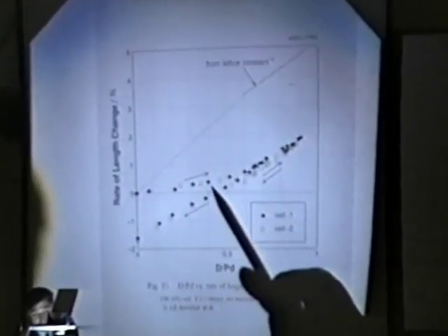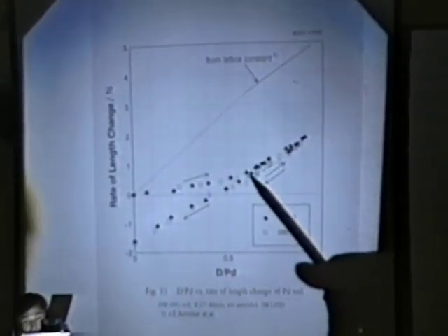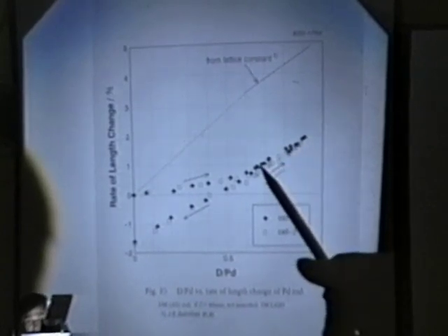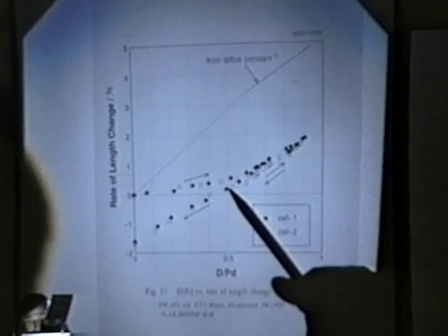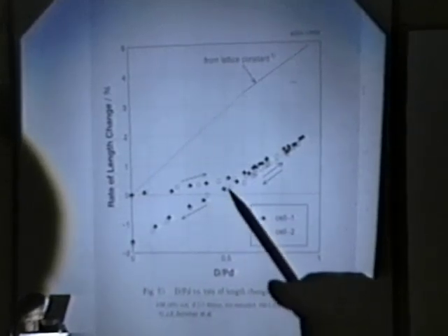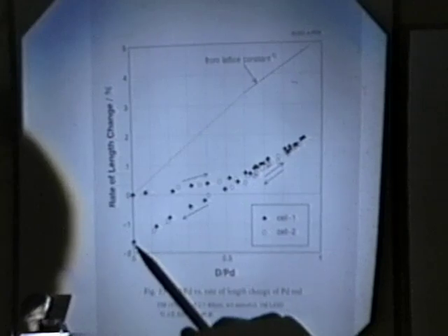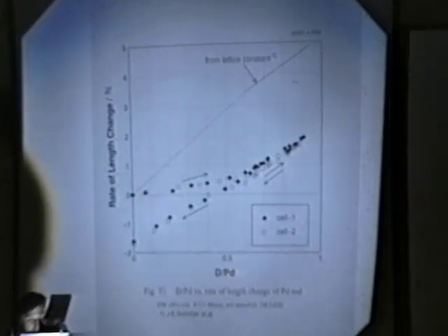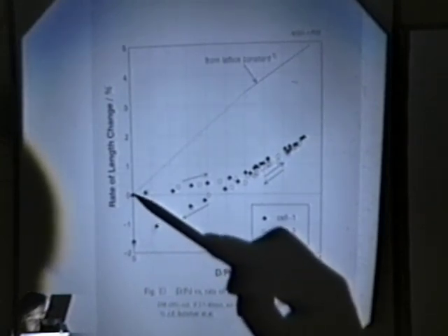So we measured the length of this palladium rod for various D over Pd and found that if we start from the original rod and increase the loading, the length increases slightly, but after the beta phase region the slope becomes sharper. If we come back, it is reversible, but when we go into the loading region of the alpha-beta transition region, the change of the size becomes irreversible. And finally, if we deload completely, the palladium rod becomes shorter than its original value, which is from here.